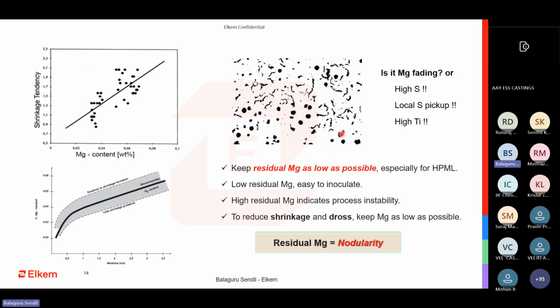When you have this sort of fading, it is more or less an inoculant that has not been able to ensure the roundness. Whereas when you have a vermicular structure like this, both the inoculant and the magnesium have faded. This is only possible in certain extreme conditions where you pour for long, or when you have a residual magnesium of 0.035 with the majority of the measured residual magnesium being free Mg. This could be the case when you are using 9-10% FSM grade with a bare minimum addition rate of 0.8 or 0.7. You maintain a residual magnesium of 0.04, 0.035, and still end up with poor nodularity or high shrinkages.